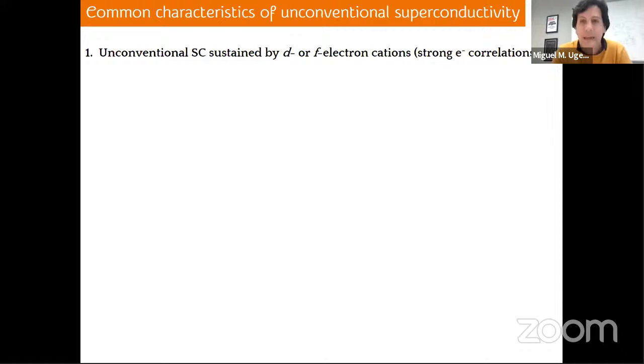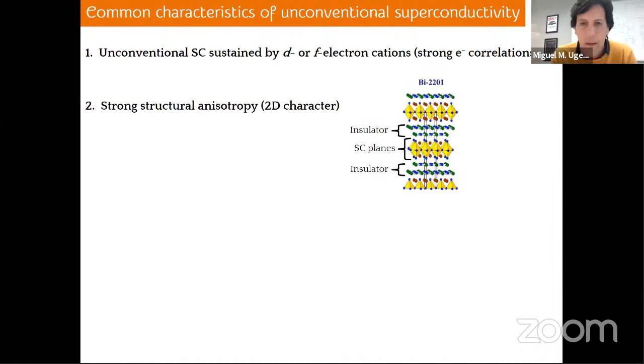These are electrons which are in general subject to strong electron-electron correlations, and lead to many-body phases. Another common characteristic of these materials is that they have a strong structural anisotropy, a strong two-dimensional character. Here I show you an example of a cuprate, where the superconductivity is basically confined within these yellow planes, and it's surrounded by insulating planes. So the superconductivity is somehow decoupled between the superconducting planes.